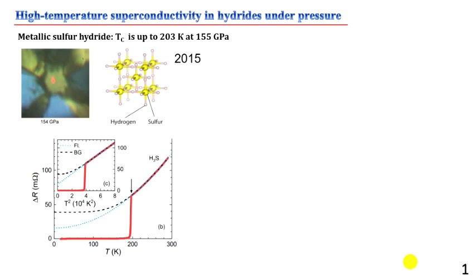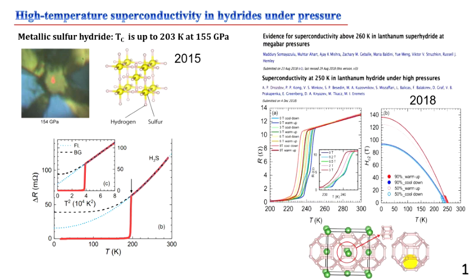As we all know, intensive studies of superhydrides began in 2015 when metallic sulfur hydride with very high critical temperature, around 200 kelvins, was discovered in Mainz, Germany by a group of Alex Drozdov and Mikhail Eremets. And then 3 years later, two groups in the United States and in Germany almost at the same time discovered another unique compound. It's lanthanum H10, which superconducts below 250 kelvins.